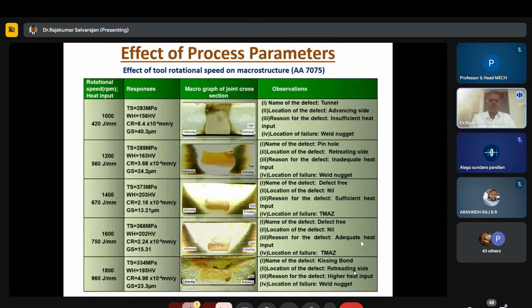You can see that at the rotation speed of 1000 RPM, the heat input is 420 joules per mm, the tensile strength is 283 megapascal, the weld hardness is 156 Vickers hardness, and for the corrosion rate we have to measure the immersion corrosion test. It is 8.4 into 10 to the power minus 4 mm per year, and the grain size is 40.3 micrometer. It ends up with a tunnel defect because the heat input is not sufficient to plasticize the material. It happened on the advancing side.